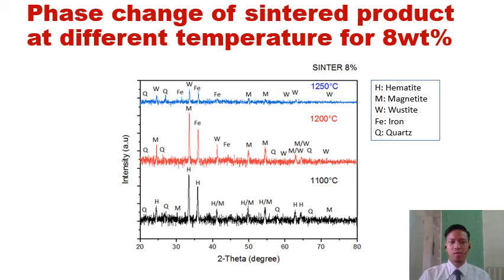Next, at 1200 degrees Celsius, the hematite has been reduced to magnetite, and some magnetite has started to reduce to wustite, with slight metallic iron phase observed, and existing quartz from the original sample. Next, at 1250 degrees Celsius, most of the magnetite is reduced to wustite, while some of it remains, and some of the wustite has been slightly or partially reduced to metallic iron phase, and the quartz remains.